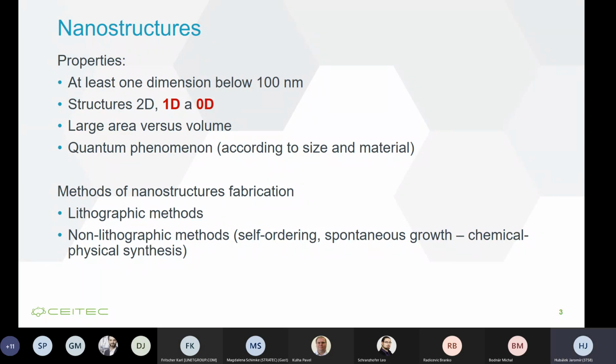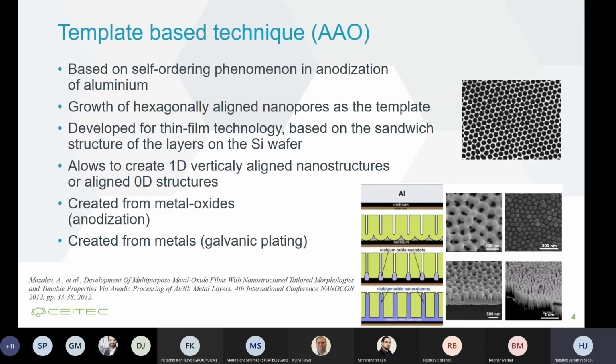What is important are our methods for fabrication of the nanostructures. It can be based on lithography, which is very expensive, of course, and also non-lithographic methods, which I will talk about mainly. These are based on self-ordering and spontaneous growth. To create nanostructures without nanolithography, we developed this template-based technique, which is based on the self-ordering phenomenon in anodic oxidation of aluminum.